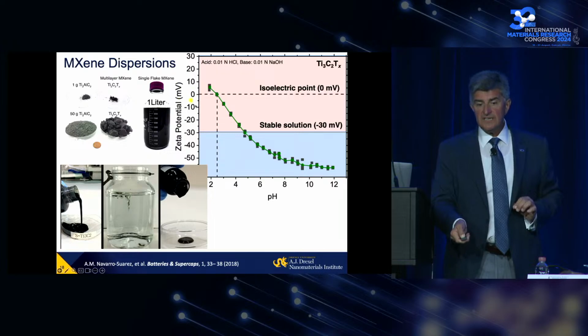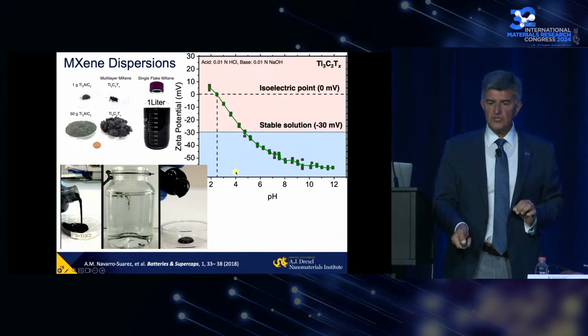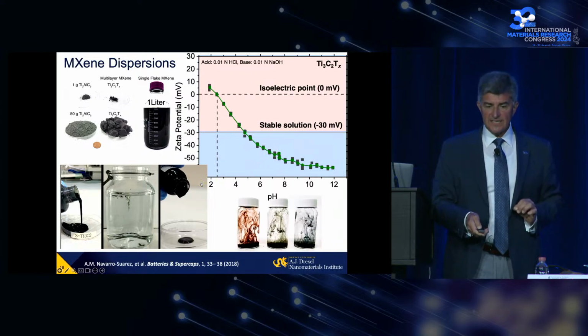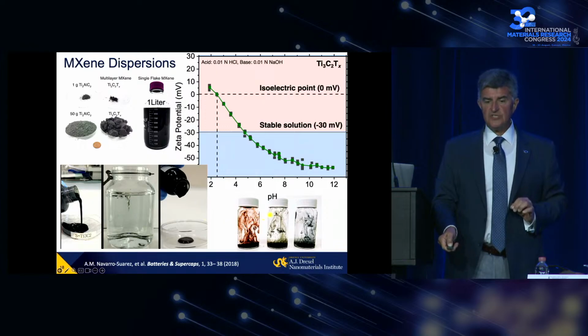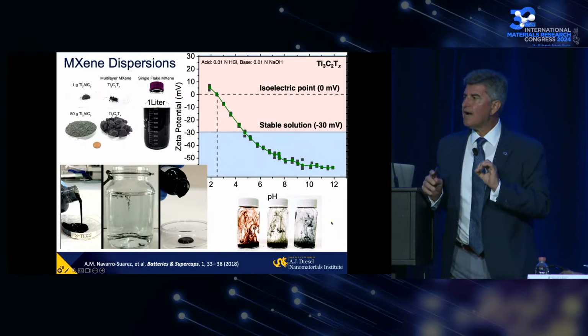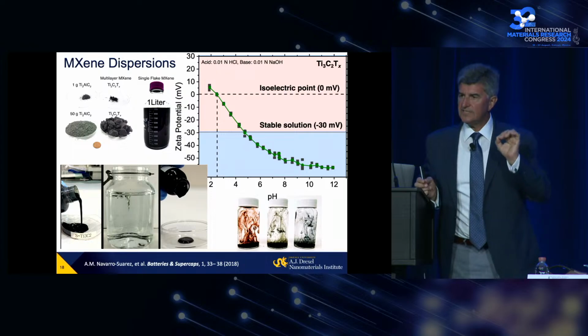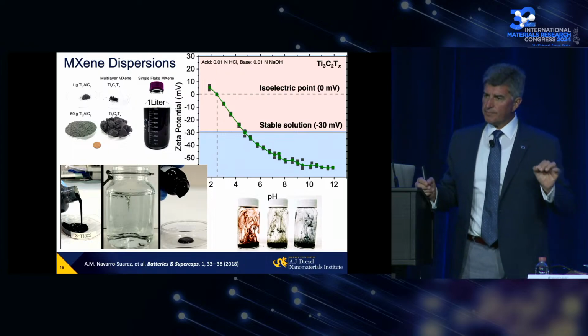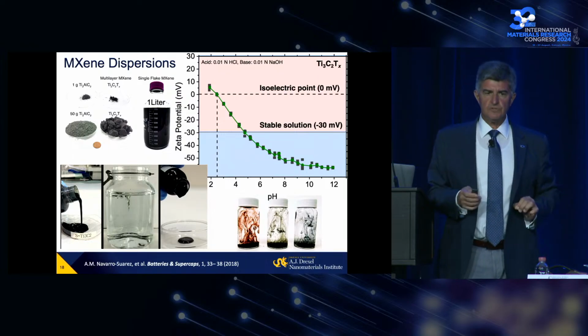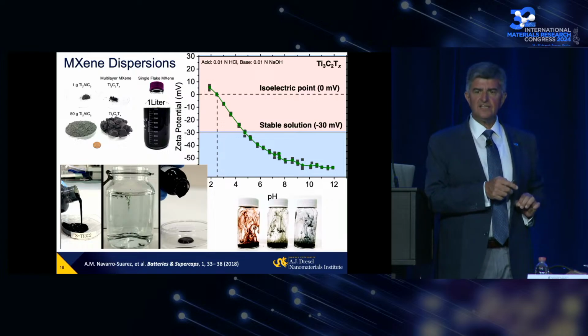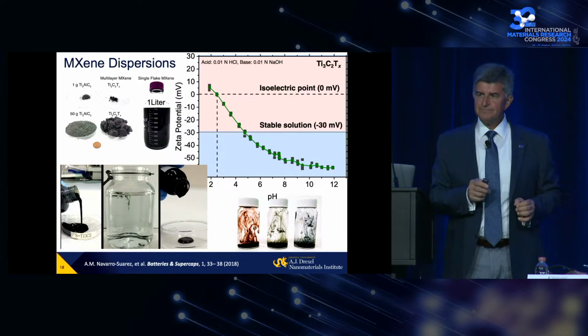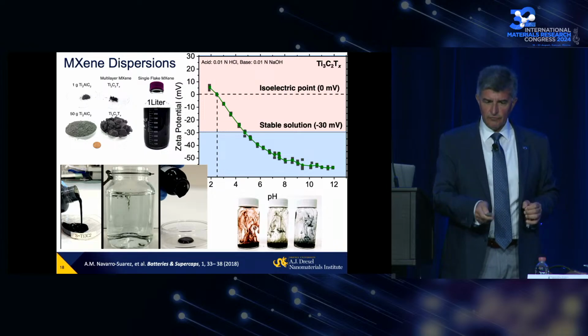There is a highly negative zeta potential as a result of this negatively charged MXene flake with oxygen and OH on the surface. As a result, MXenes dissolve in solution, and they also come in different colors. This means optoelectronic properties are different, but also you can make things not only shades of gray, but really colorful.